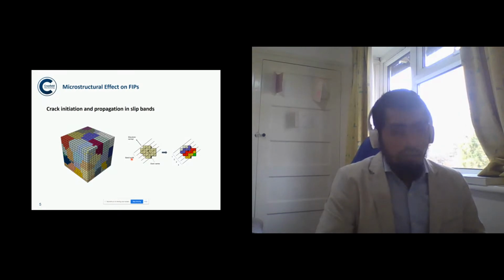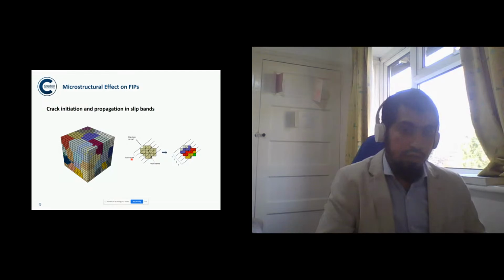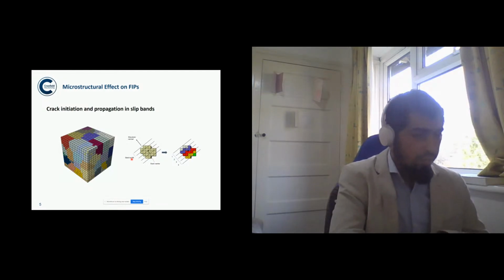So for this one, we have created a finite element model with roughly 50 grains to study the effect of microstructure on FIPs. The literature showed that microstructure-sensitive small fatigue cracks initiate and propagate along the slip bands. Following on, we have created artificial slip bands in each of the grains along the crystallographic direction. And in this study, we're going to investigate crack initiation and propagation along the slip bands.